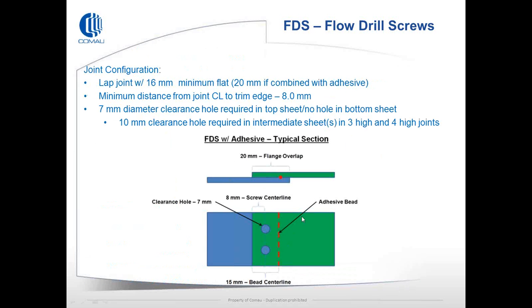Typical joint configuration. This is showing a lap joint with an overlap of approximately 16 mm, 20 mm to the edge if there's adhesive. 7 mm clearance holes are required sometimes on the top sheet, depending upon the actual stack-up configuration, and a 10 mm clearance hole, depending on the tooling variability, etc., in the lower sheets.